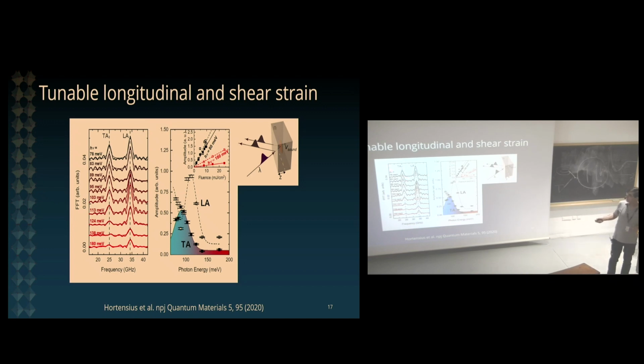So the excitations of these transverse and longitudinal propagating strain waves can be strongly influenced by coming in and out of resonance of this phonon mode. So we are always exciting both modes, but the efficiency in which we excite the longitudinal mode and the transverse mode depends strongly on the exact photon energy that we are using for this experiment. So when we are tuning, this peak is the phononic resonance that we are exciting, and here you see the amplitude of the longitudinal mode and the amplitude of the transverse mode, and the two seem to be competing with each other. So one peaks and the other one has a dip.